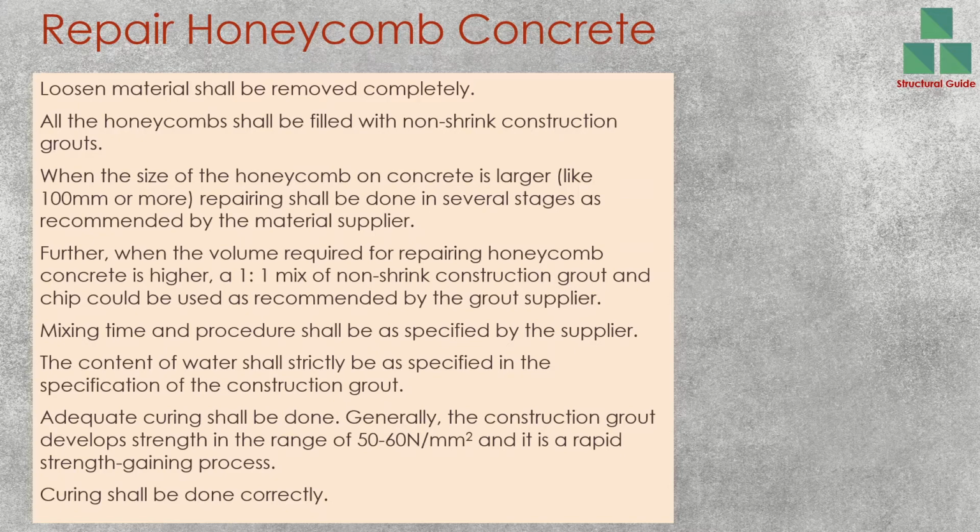Also, I have to mention the water content again. You have to make sure the adequate water, as specified in the supplier's specification, is used for the mixing. Otherwise, there may be cracks in the non-shrink grout also. Due to higher shrinkage or drying shrinkage, there may be cracks in the concrete if you add more water than is specified. Therefore, you have to be careful when you do the repairing with non-shrink construction grout.